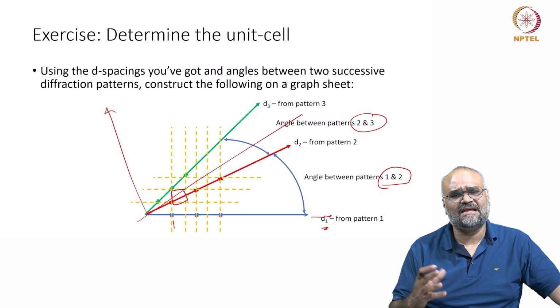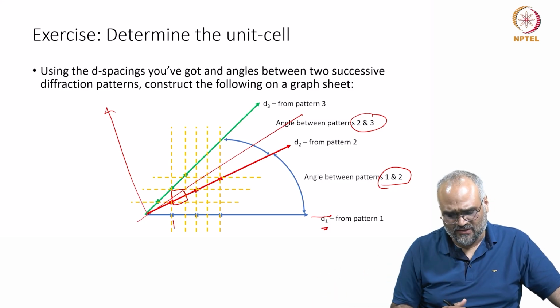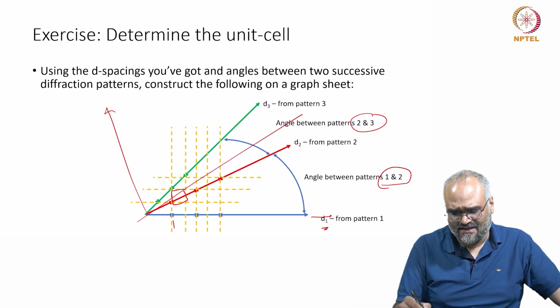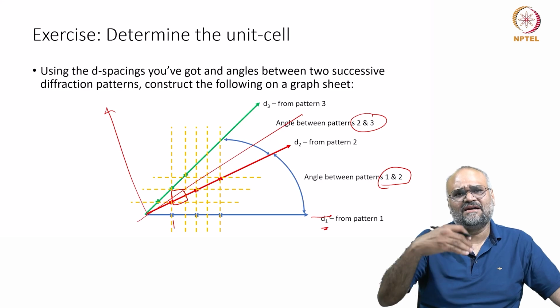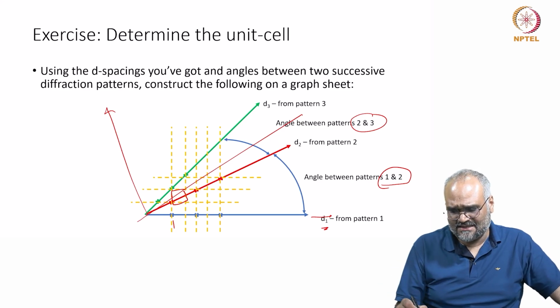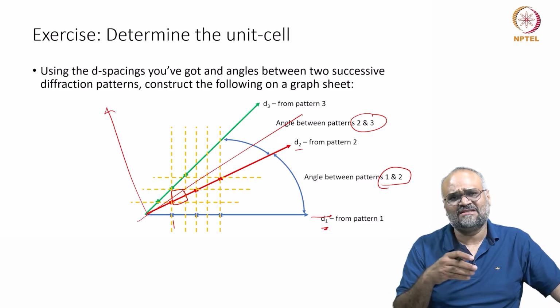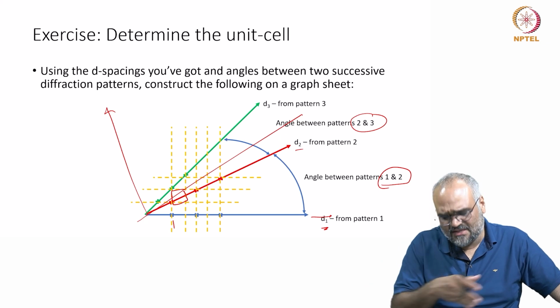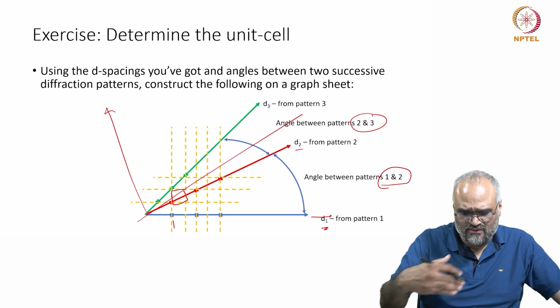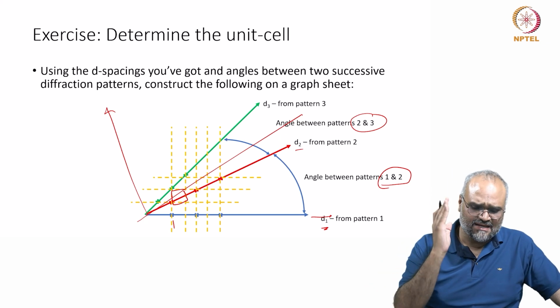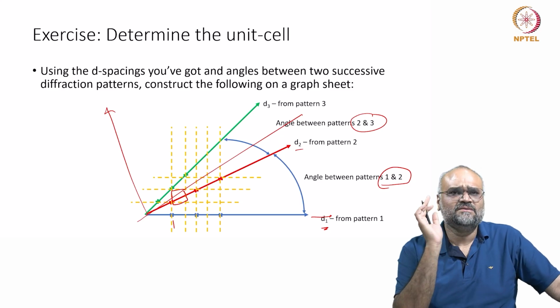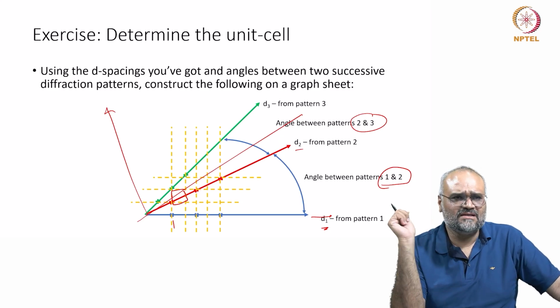It depends on the angle that you can rotate in the microscope, and having more and more such intermediate reflections and the d-spacings from diffraction patterns from whatever zones or nodes you can achieve through the total tilt range, by maintaining a common axis, would give you a very accurate determination of the unit cell.